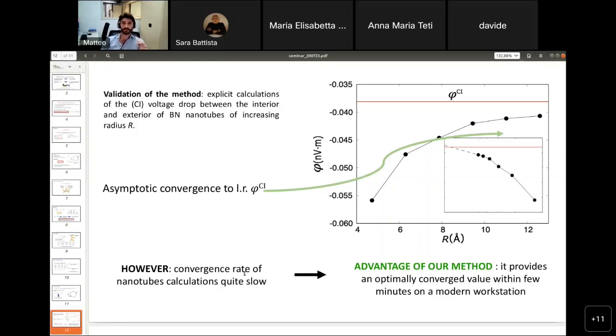So what we did was perform explicit calculations on boron-nitride nanotubes of increasing radius. And particularly, we did it at the LDA level, just to reduce the computational effort. The brute force method shows that there is an asymptotic convergence to our linear response method. But at the same time, it highlights the advantage of our method, because we can see that the rate of the convergence is quite slow. Indeed, even for the biggest nanotube considered, that is constituted of more than 100 atoms, the deviation with respect to the convergence value is still about 10%. Then we can see the advantage of our method, that conversely provides an optimally converged value with a much less computational effort.